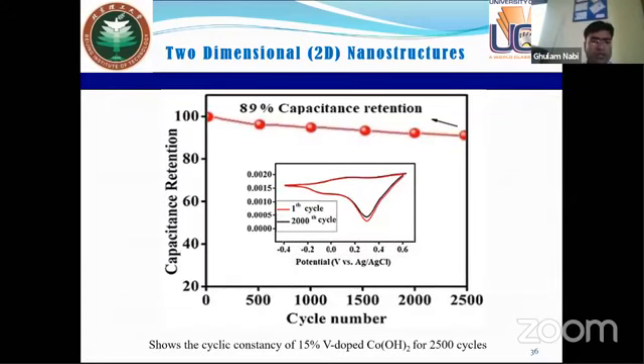Here are the two-dimensional nanostructures, and we can see here the cyclic consistency. Actually, for cyclic consistency, if we use any material, that material should be very stable. If the stability of the material is not good, it cannot be used for the supercapacitor. So here you can see we have used it for 2500 cycles, and its capacitance retention is 89%, which is good enough for utilization in supercapacitors.